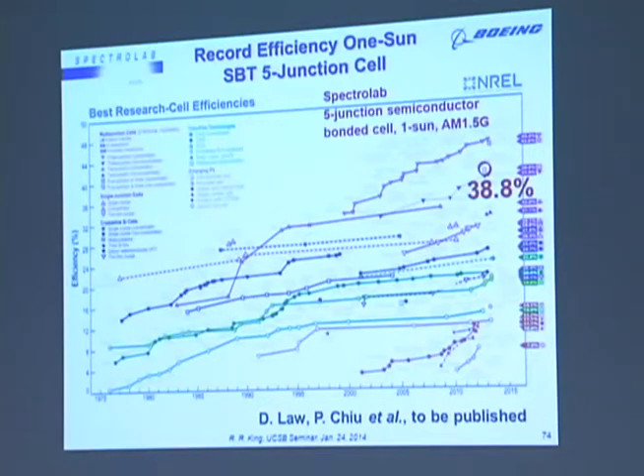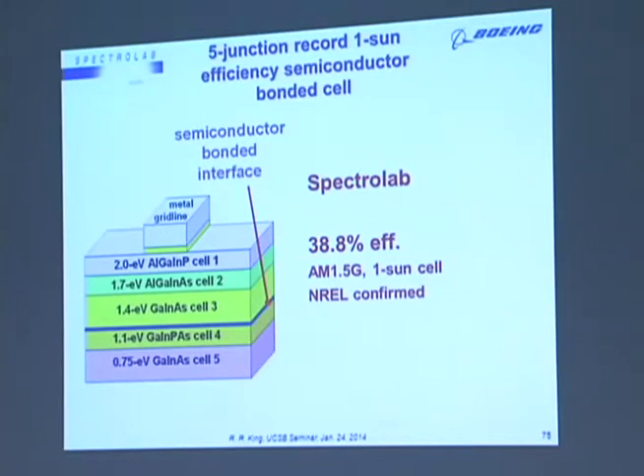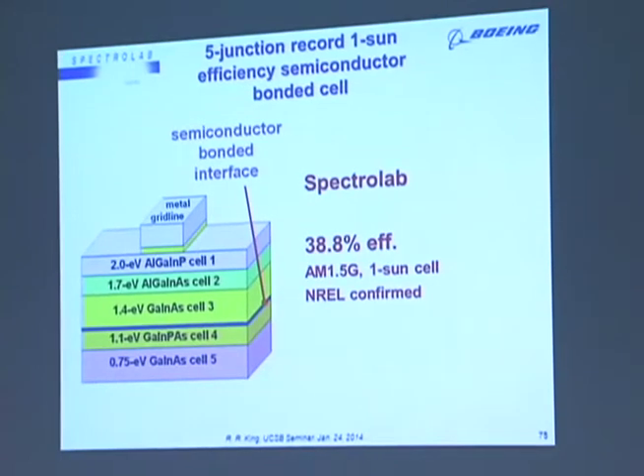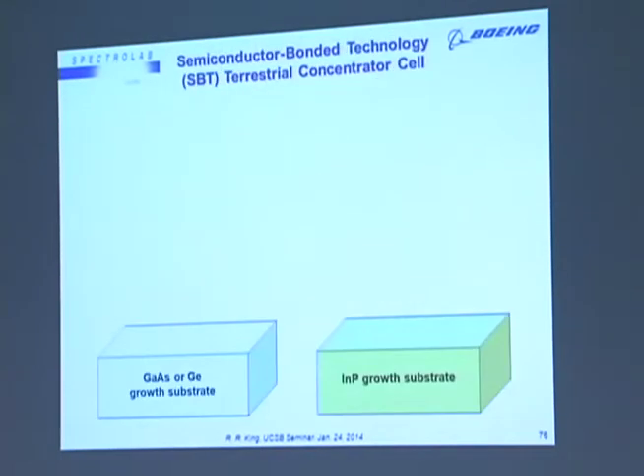And another recent result that Spectrolab has achieved is a 1-sun cell result, also using wafer bonding. But this is a 5-junction cell, and it's at 1 sun, so the efficiency is lower, but it's a record efficiency at 38.8%. And the structure of that cell is shown here, a 5-junction cell. And you can see the cell construction a little bit more clearly on this plot.